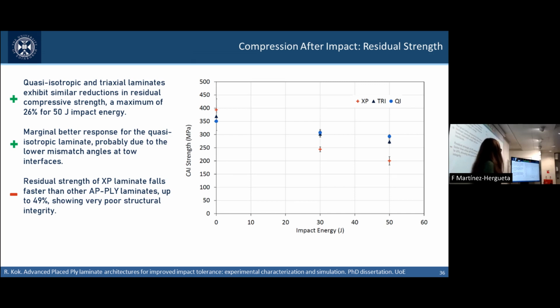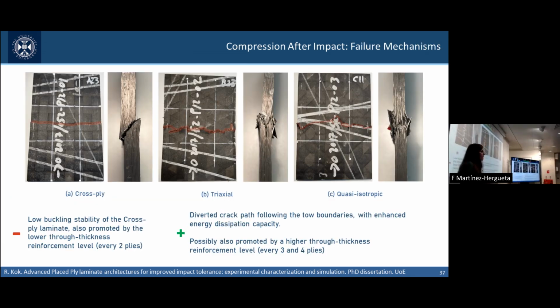The laminate that has a different trend is, of course, the cross-ply laminate, with a reduction in compressive strength of 49% when subjected to 50 joules of energy. So one of the reasons why it's performing worse is the larger delamination footprint, but it also has to be related to the main failure mechanisms that are triggered. The cross-ply laminate presents very low stability to compression and presents a very clean crack all over it, very, very straight.